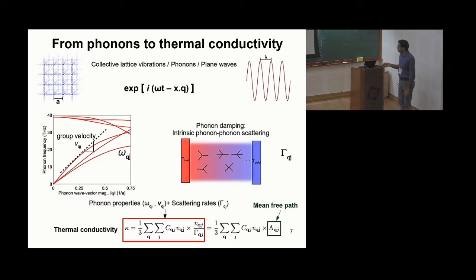So there's also another form which may be more familiar to you. V over gamma has a unit of length, and that's given by the mean free path of phonon. So thermal conductivity K is written as a sum over individual phonon modes in the solid, CV times the mean free path.